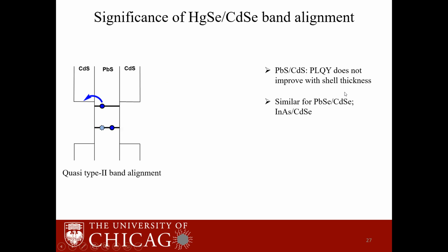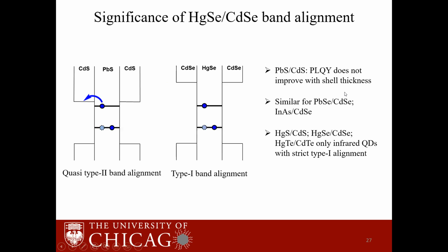So it is observed that as you grow a thicker shell, you do not observe an increase of the quantum yield. And this is not just true for lead sulfide, but also for other shortwave infrared materials like lead selenide and indium arsenide. All of them have a quasi type 2 band alignment, and we don't see an increase in the quantum yield as a function of shell thickness. But from our knowledge, the only materials which have a strict type 1 band alignment are the mercury chalcogenides: mercury sulfide, mercury selenide, and mercury telluride. Although they have the issue of toxicity, there is no other material which has this band alignment, and this is the only way right now to get brighter materials in the shortwave infrared.